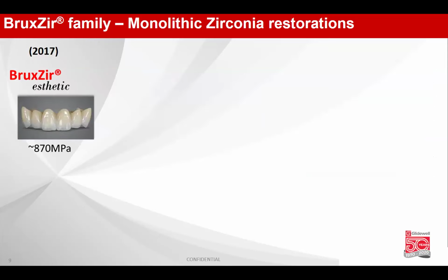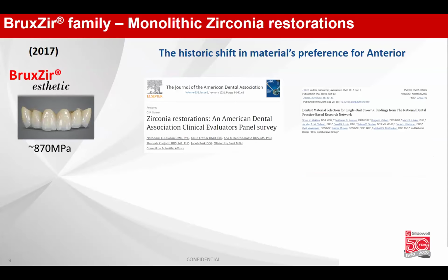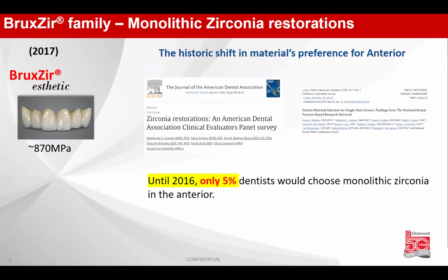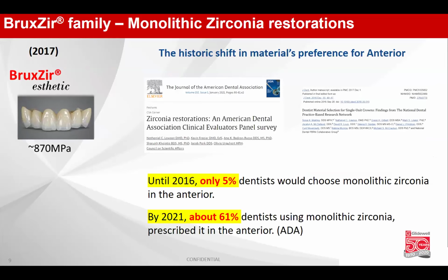Then in 2017, Bruxer Aesthetic was launched, which is about an 870 MPa product line. And there we can see that there was a historic shift in the market's material preference for anterior. Why we are saying that is already published in an article in the American Dental Association. It says that up to 2016, only 5% of dentists would choose monolithic zirconia for anterior regions, mainly because of the aesthetic issue. And by 2021, up to 61% of dentists started using monolithic zirconia for anterior regions.